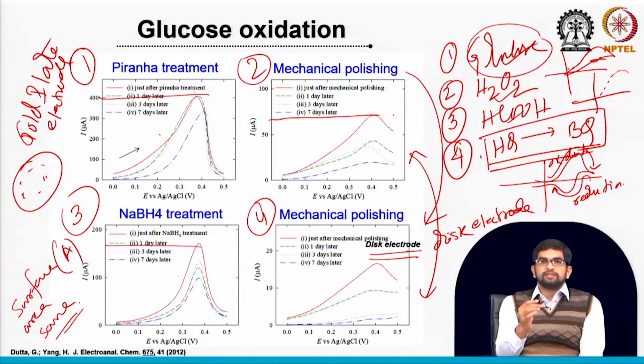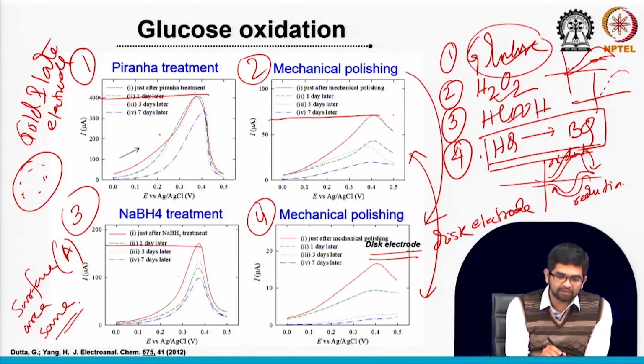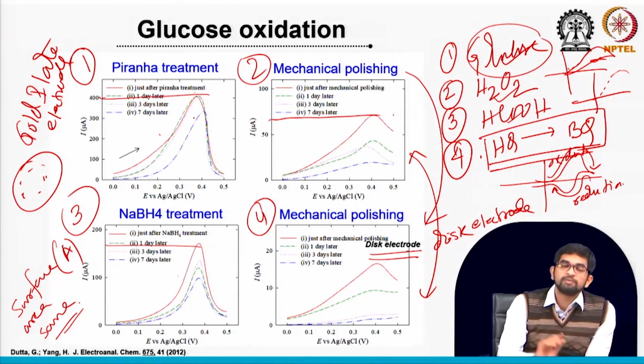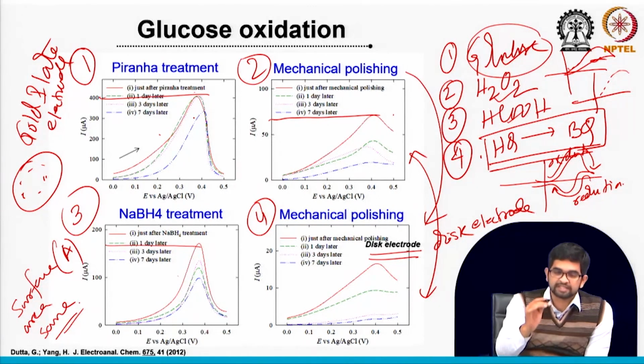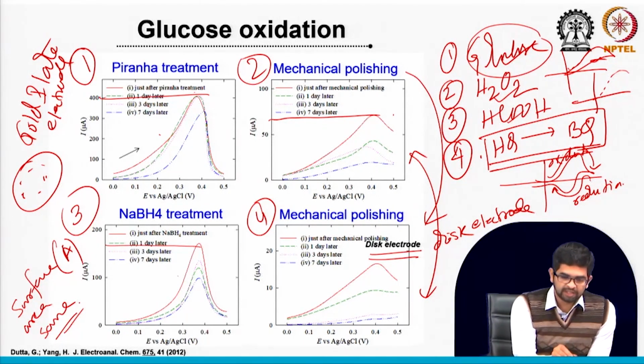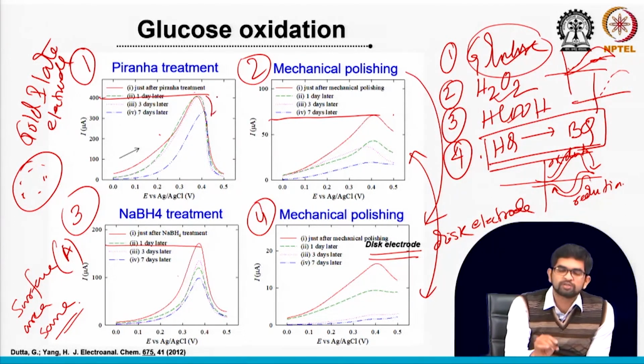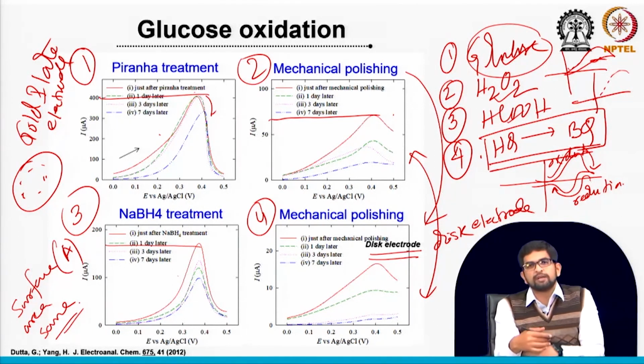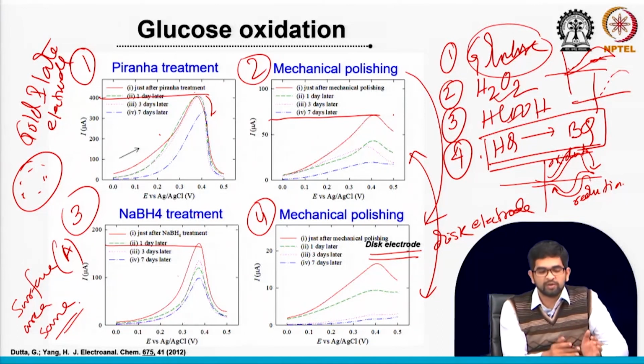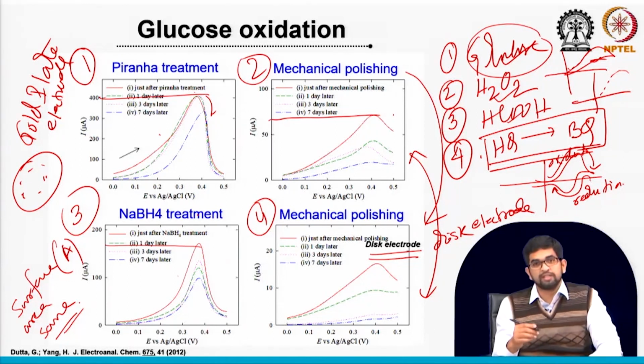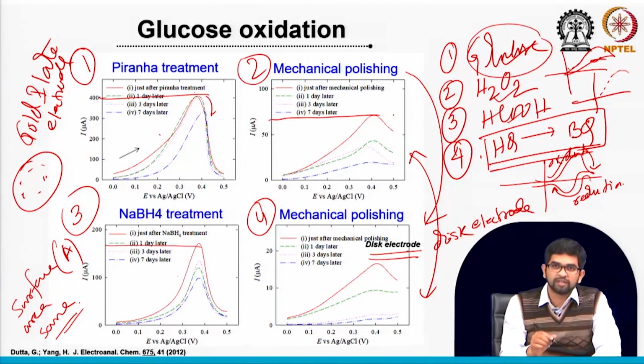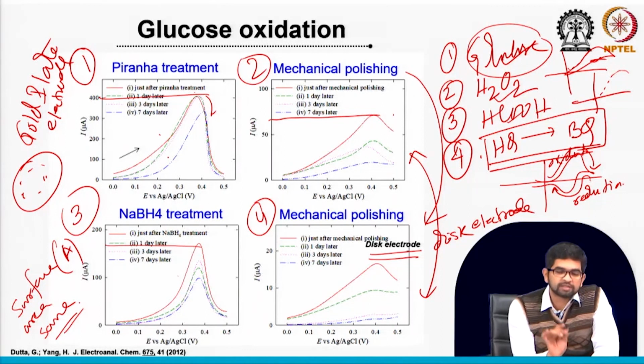Now let us compare their deactivations. One important phenomenon we can observe here is that when the treatment activates the surface strongly, deactivation is also slow. After 1 day, 3 days, 7 days, it changes very slowly. Why is it changing? Because we are not taking many precautions about the storage condition. We are simply storing in the lab environment. So there may be some change, but I will show you all the factors later: the contamination factor, whether there is a reconstruction effect or not, with XPS and AFM studies. So the interesting phenomenon is that if your surface is highly activated, deactivation is also a little slow.